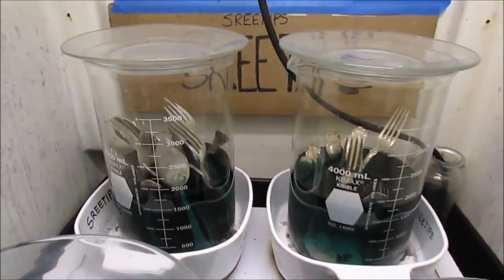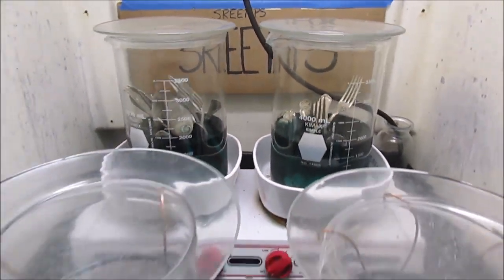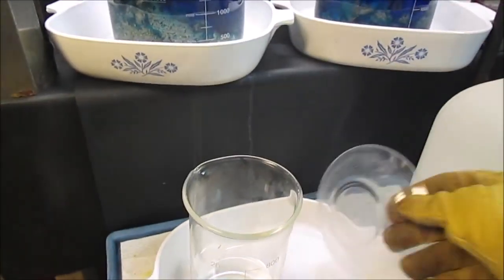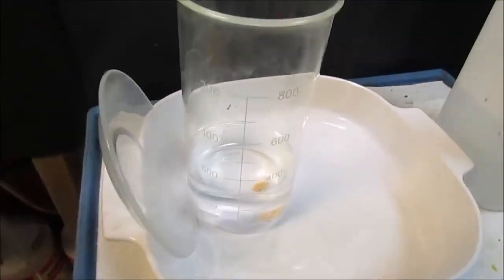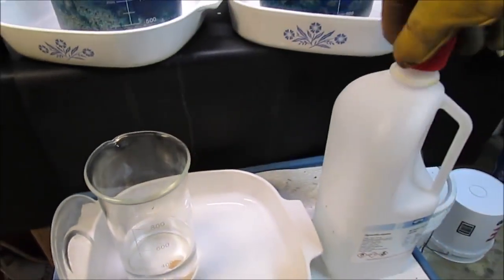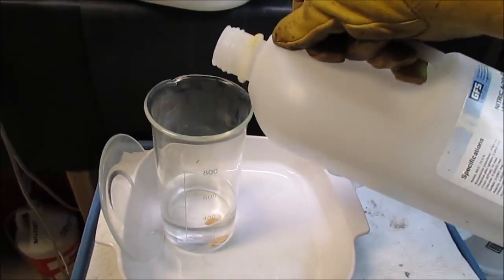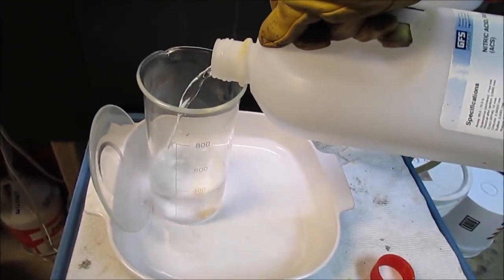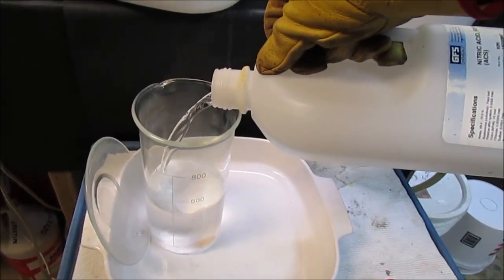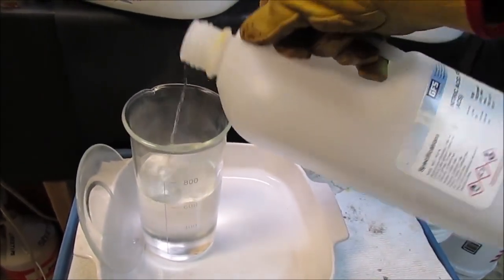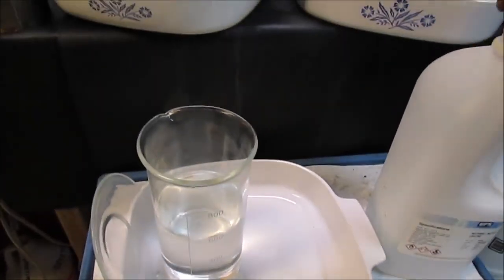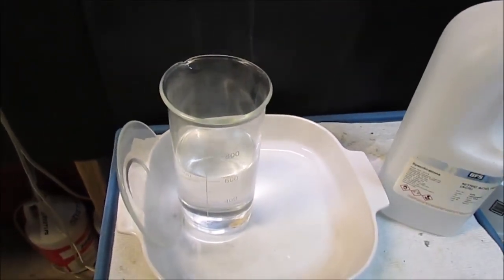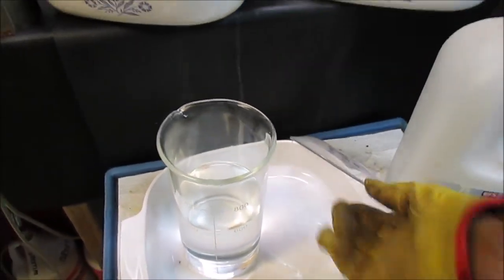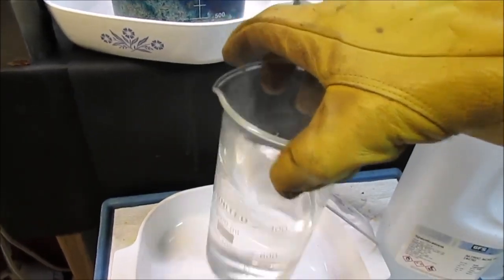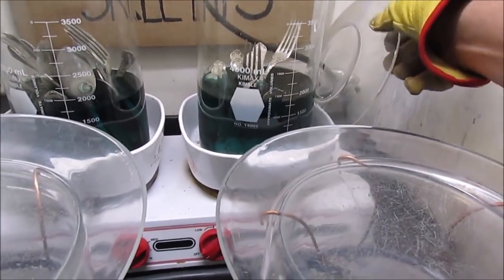Here I've got the flatware still dissolving. I'm going to start this off with about 300 ml of distilled water in our beaker here. I'm going to add some nitric acid to make a 50-50 solution of dilute nitric acid. And then I'm going to add some of that to the silver flatware up here. I'll get this started back up.